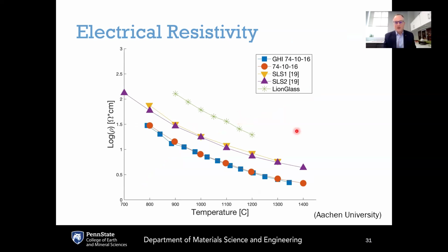This is work that was being done by Christian Roos and his group at Aachen University. They measured the electrical resistivity of molten LionGlass and compared it to soda lime silicate. You can see that the resistivity of LionGlass is just slightly higher at the same temperatures as soda lime. But given that it's in the same ballpark, this means that this is compatible with electrical melting, which of course is important to go to lower carbon glass melting furnace designs.